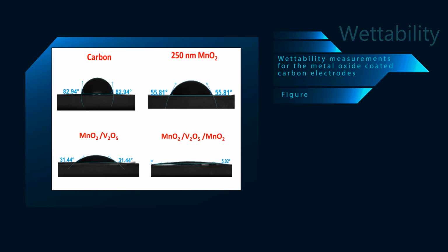It is also worth mentioning that the hydrophobic nature of carbon electrodes was altered by the metal oxide coatings. The selective coating approach not only introduced redox effects, but it also transformed the carbon's hydrophobic nature to a superhydrophilic nature, as shown in the figure.